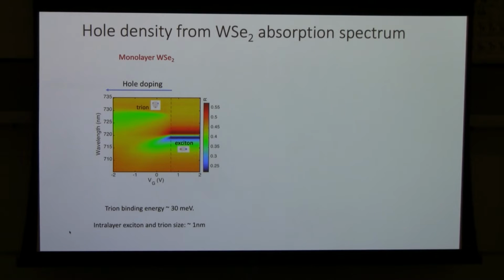This is an intralayer trion, where the exciton excited in WSe2 is bound with a hole to lower its energy. The energy is lowered by about 30 meV, which is the energy difference between these two states. So the trion binding energy for this intralayer system is about 30 milli-electron-volts. People have also done a lot of calculation and characterization to visualize the exciton and trion behavior. This intralayer exciton and trion have a characteristic size of about 1 nanometer. So they are very tightly bound.